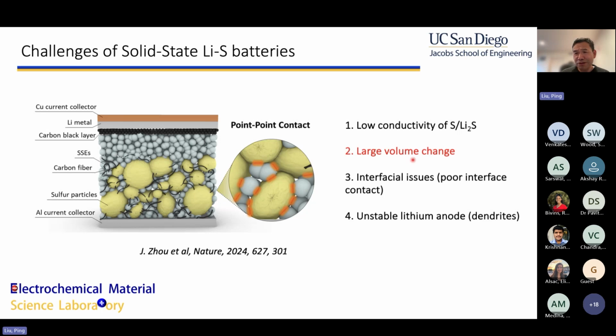To make it even worse, sulfur expands a lot when it makes lithium sulfide. In the liquid electrolyte, that's not a big deal because the polysulfide dissolves and reprecipitates. In a solid state, if something expands and shrinks, then the structure cannot recover. So you create a lot of issues at the interface.